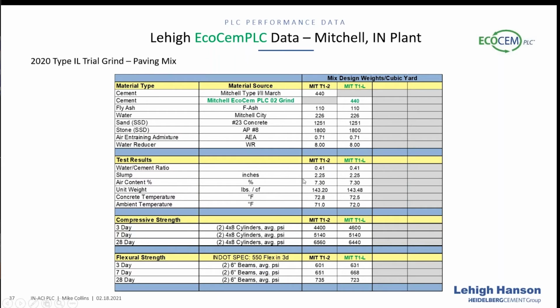Air was 7.3%. As we go down into the strength data, focusing from the paving standpoint on flexural strength, we had 631 PSI of flexural strength in 3 days, 668 in 7 days, and 723 PSI in 28 days. Again, really outstanding performance, and it did as good or better than the Mitchell Type 1, which has been used with a lot of success in paving to date.